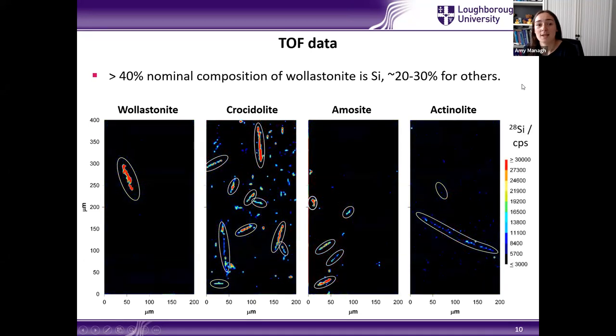I'm now showing the silicon data. We measured 28 silicon. I should say that the time of flight system that we used here has an always-on collision reaction cell, which means that we're able to reduce or remove nitrogen and argon-based interferences. So we were able to measure 28 silicon here.